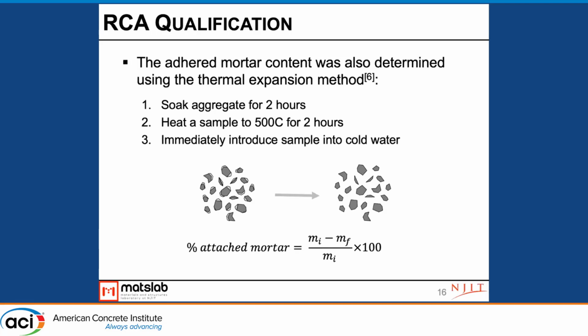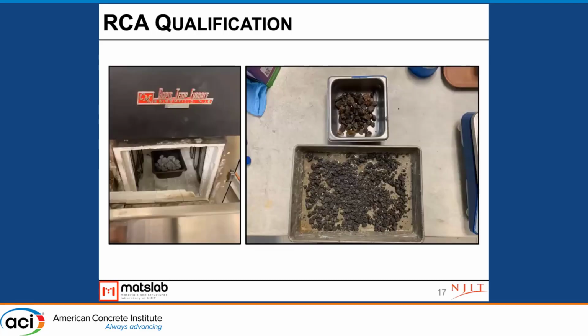So this process involves soaking the aggregate for 2 hours, and then heating the sample to 500 degrees Celsius for 2 hours, and then immediately introducing the sample into very cold water. What this achieves is it shocks the mortar matrix, and it causes it to disintegrate and fall away from the natural aggregate phase. What happens during this process is that some natural aggregates may be split, but they do not disintegrate. So what this enables us to do is to look at the percentage of that system that is attached mortar. This is just to give you an idea of what this looks like.